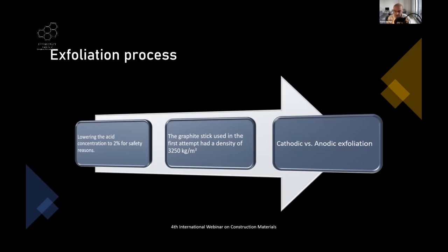So we corrected our mistake and switched the positive and negative electrodes. In addition to that, we tried a looser stick with a lower density of 2,540 kilograms per cubic meter. We applied 12 volts DC current again, and this stick completely exfoliated into graphene oxide after 24 hours. The next step was to improve the quality of the acquired GO, that is graphene oxide, by means of ultrasonication.